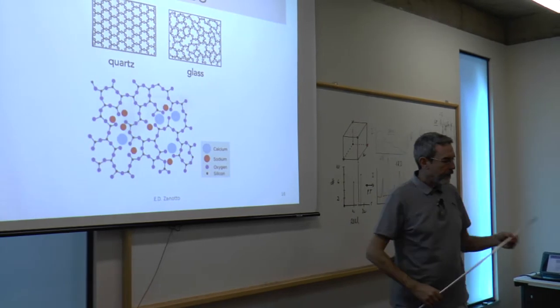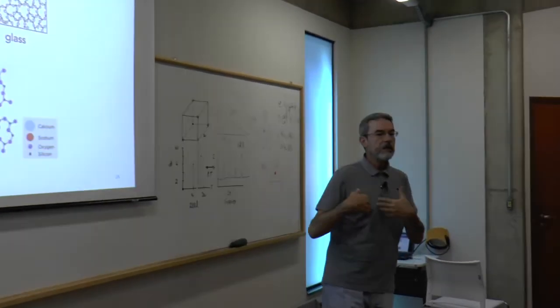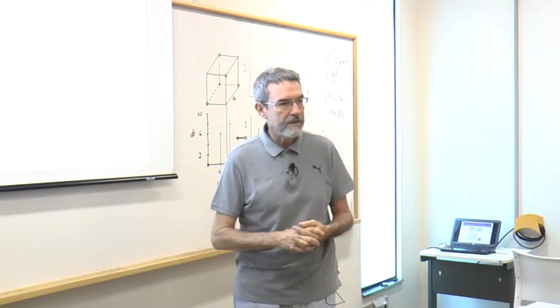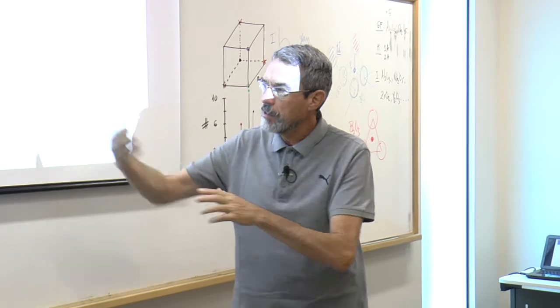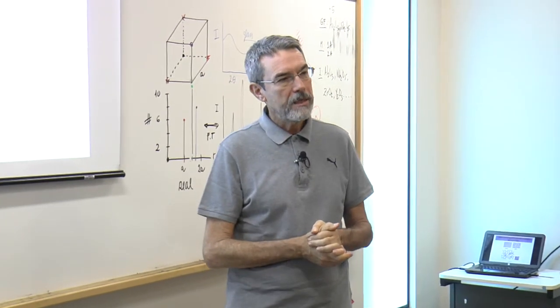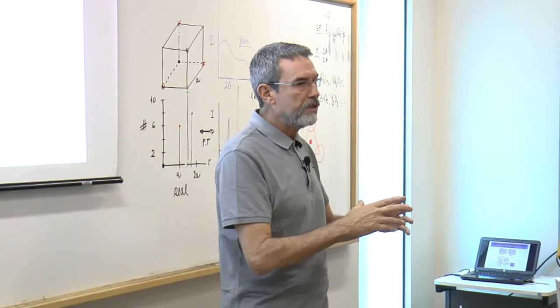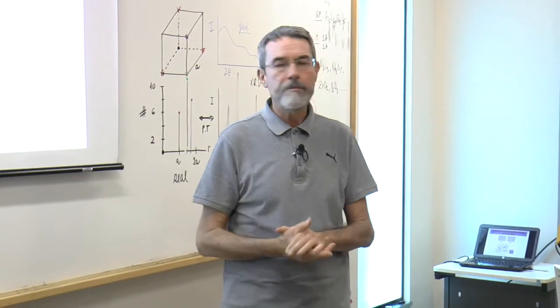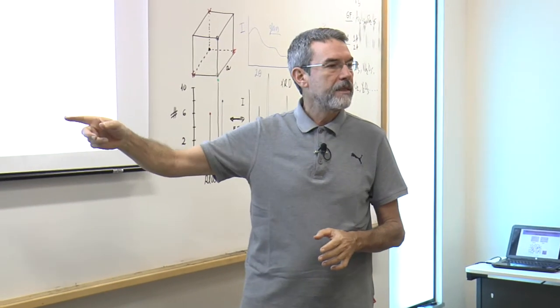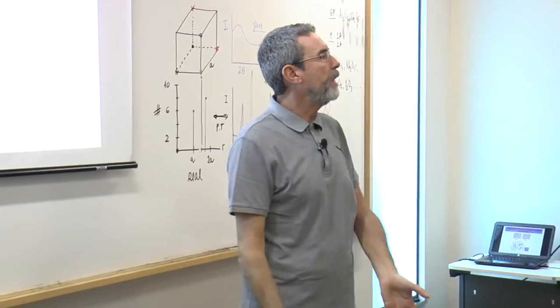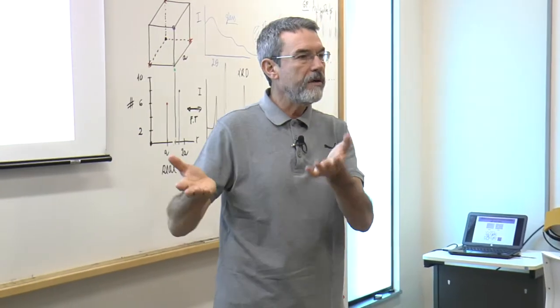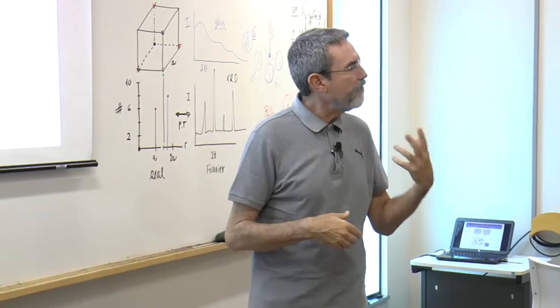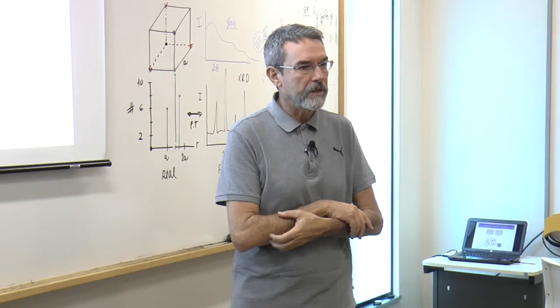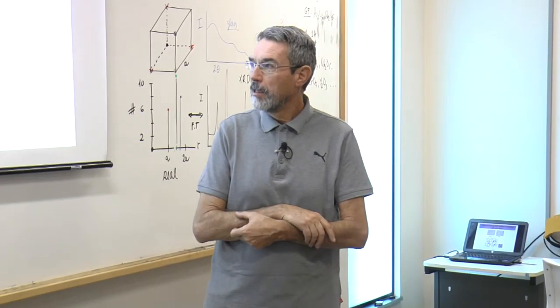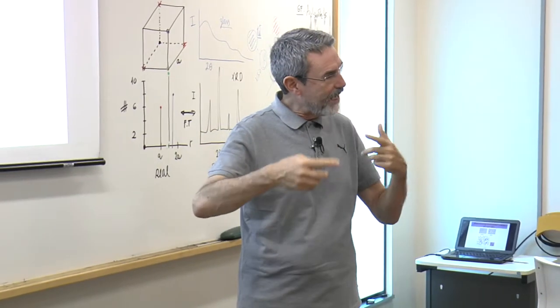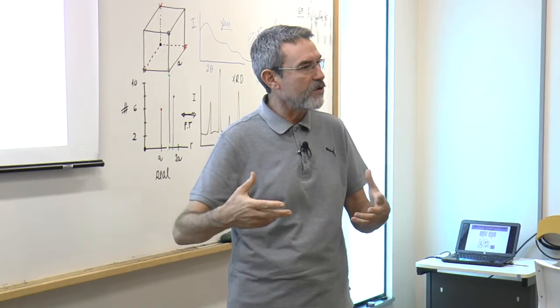So you're becoming more and more familiar with the structure of glasses. The effect of this modifier oxides is to break bridges and form other types, more ionic type of links. In doing that, the viscosity decreases, the solubility increases, the thermal expansion coefficient increases. You already start to have a feeling on the effect of these materials on the properties of the glass. And the number of Q3 units changes, Q4 units change, and so on.